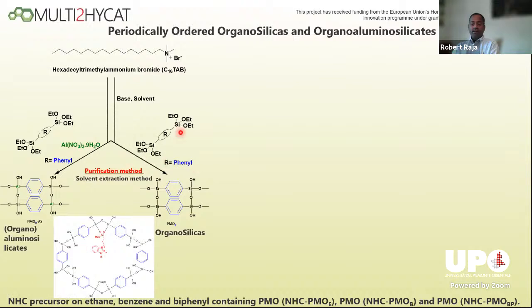So here is an example where you just introduce the organosilane moiety, and you can embed these organic groups within these periodically ordered mesoporous silica. Now, if you want to introduce some acidity within the system, you could make these periodically ordered aluminosilicate materials where you can replace some of these silicon atoms with an aluminium site. So now you have almost a bifunctional catalyst. You have an acidity introduced within the material, which can work in concert with these hydrophobic groups to impart some interesting catalytic trends and potential.